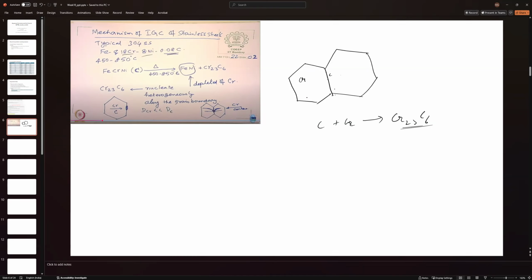So carbon will migrate toward the grain boundary, and so will chromium. Near the edge, close to the grain boundaries, you'll have depletion of chromium because it's migrating toward the grain boundary and forming precipitates there. This depletion in chromium leads to losing the passivity which chromium was providing, and hence you get corrosion around the grains.